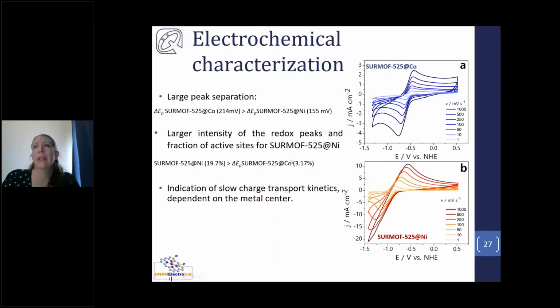But more interestingly, what we see is that the peak separation for the cobalt MOF is around 214 millivolts, whereas for the nickel it is 155. So it's way larger in the case of cobalt. This is a strong indication that this charge transfer kinetics is even slower on the cobalt MOF, and that is dependent on the metal, which we really didn't expect. As a result of this poor kinetics, we see that the peak intensity for the MOFs is different.